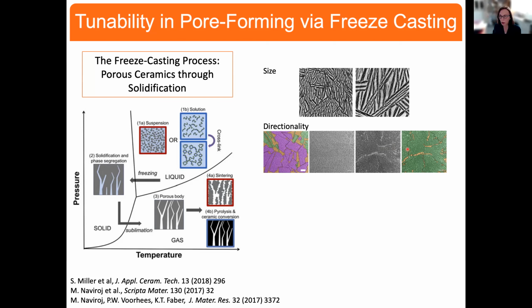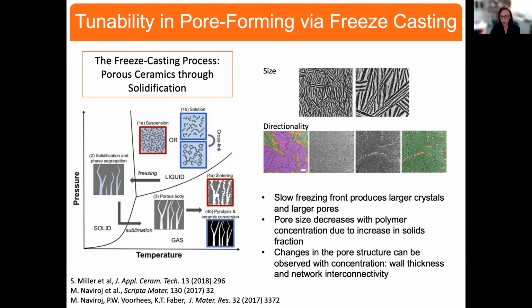And so with the appropriate template, we can get a structure where you're looking at the surface, this colorized surface, to tell you what percentage of the pores are basically facing out at you. And we can do that, as you can see, quite successfully compared to the image on the left, where the purple indicates that the pores are off axis.